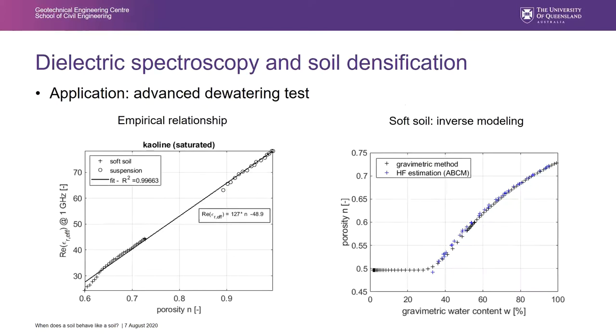So we are finally able to reach, here on the left, this very empirical relationship, which works very well. But for suspension and soft soil, we are able to directly correlate the permittivity measured at 1 GHz with the porosity, with an extremely good correlation coefficient.